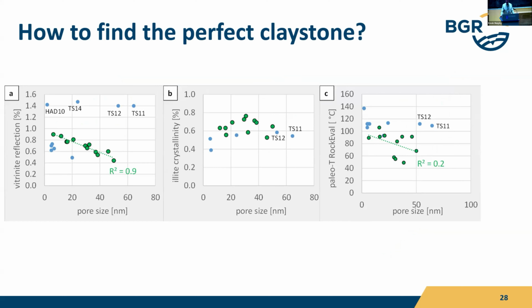We have not considered the pore size as a possible parameter telling us something about the clay. When we look at the comparison of pore size with vitrinite reflection, we find a nice graph of the green samples, but the blue ones are absolutely out of the range, right? And these are the samples from the geothermal anomaly, which is quite clear. So the vitrinite reflection there is high, but the burial depth was not that high. So if you have a geothermal anomaly, then you would be able to guess the burial depth from the pore size, but not from vitrinite reflection.